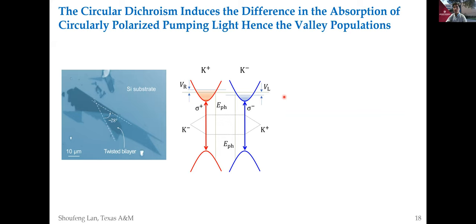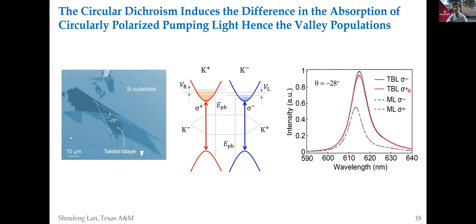As a result, the emission of the two valleys, theta plus and theta minus, will be different as well. During the experiment, we observed that theta minus, the blue curve, is larger than theta plus. The reason is that the twist angle, in this case, is minus 28 degrees, or counterclockwise. For comparison, we also measure theta minus and theta plus from a monolayer WS2 on a silicon substrate. We know that monolayer WS2 does not have the twist-induced chirality. So we observe that theta minus and theta plus are the same, evident by the overlapping dashed curves over here. This control experiment verifies that we observe the excitonic chirality in the twisted bilayers, and it also shows that we have corrected all the errors during the measurements that can induce circular polarization.